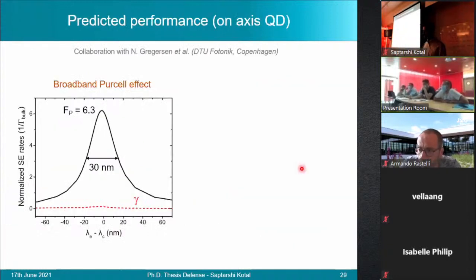Now, the device performance simulation was performed by our colleagues in Denmark. And here we plot the normalized spontaneous emission rate as a function of the emitter wavelength detuning with respect to the cavity mode. At resonance, we expect a maximum normalized emission rate of around 6.3, and a significant acceleration is maintained over a broad bandwidth of the order of 30 nanometers. Additionally, we observe that the emission into the radiative modes is strongly suppressed across a much larger spectral range.